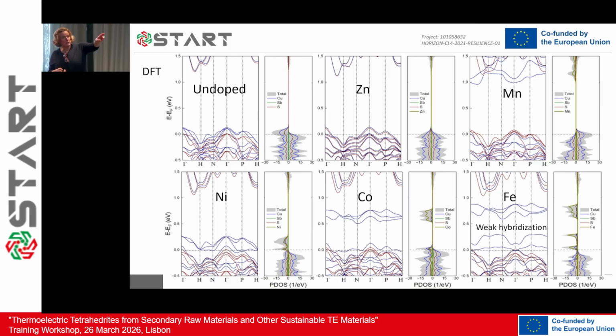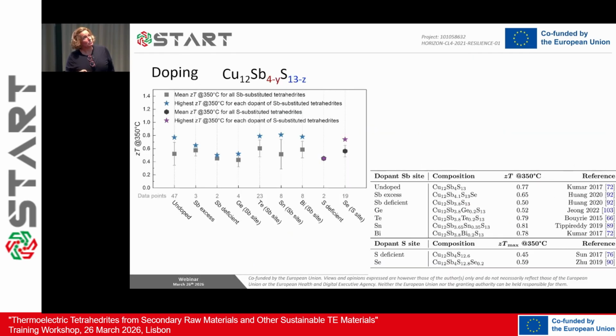But all of them tend to decrease because what happens is that the dopant electrons tend to fill in the holes in the valence band, and this means that the Fermi level goes into the band gap and the material starts to behave insulating. So I'm almost done.